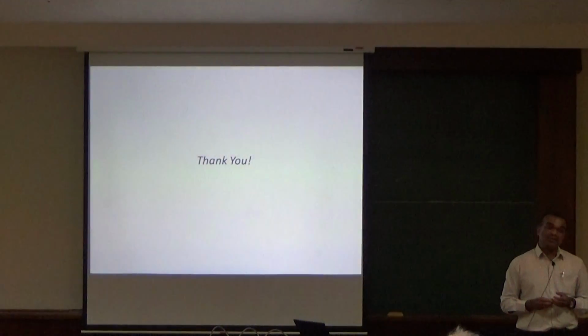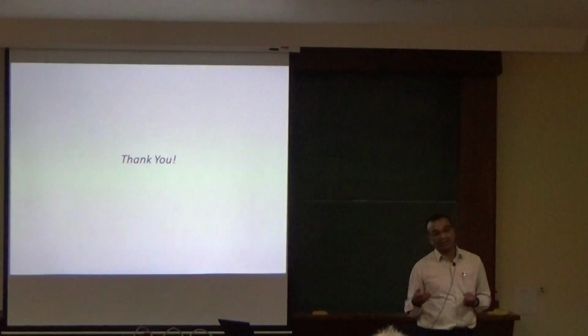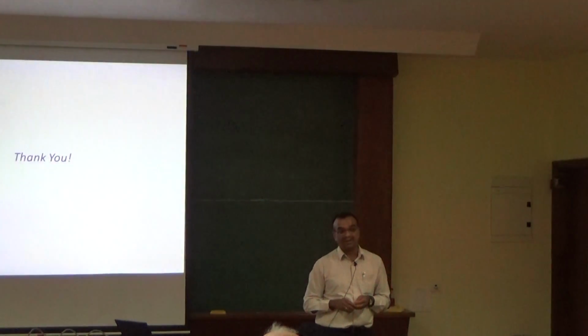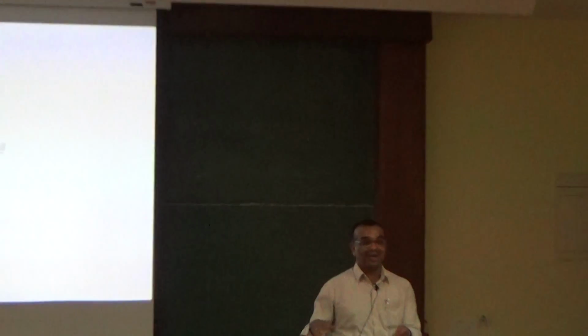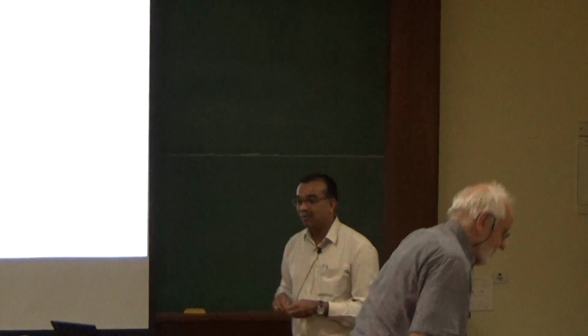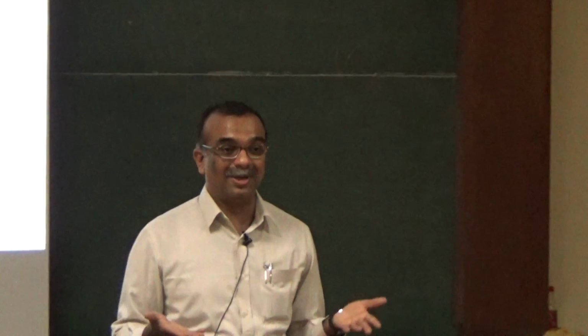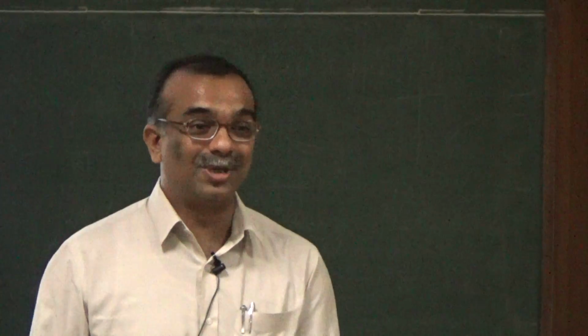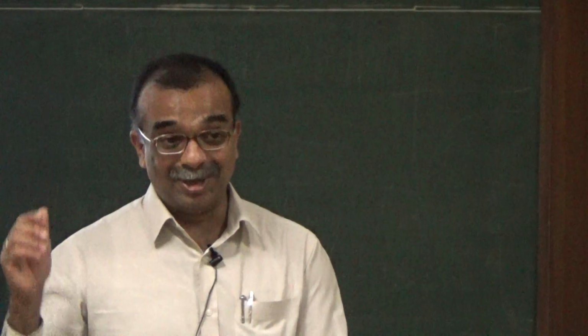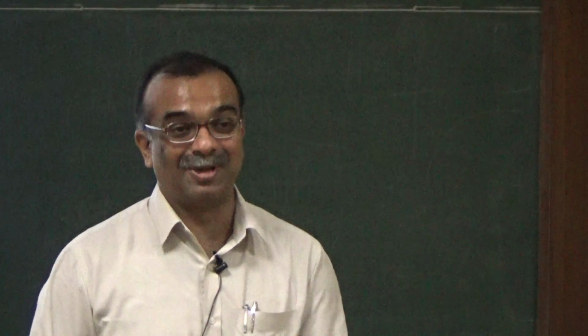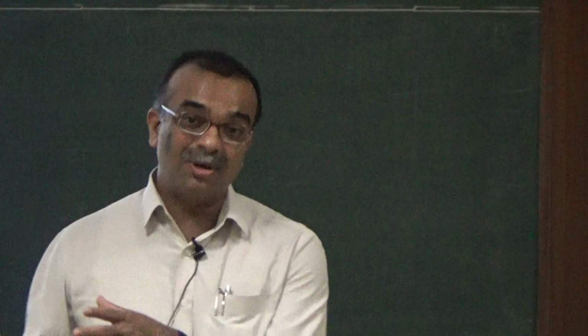Okay, 2H is the most stable form. So if you generally make MoS2, that's the form it will take. The 1T structure, people had made by what is called lithium intercalation. This was in 1999. Actually, after we did this work, we found a paper by Mercouri Kanatzidis where they had done lithium intercalation to study MoS2, not with the intention to see whether the 1T form stabilizes, but they did see trimerization, which is our prediction. Okay, so that was long ago.